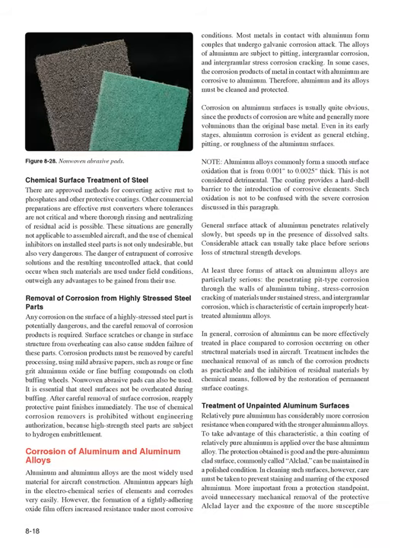Chemical surface treatment of steel. There are approved methods for converting active rust to phosphates and other protective coatings. Other commercial preparations are effective rust converters where tolerances are not critical and where thorough rinsing and neutralizing of residual acid is possible. These situations are generally not applicable to assembled aircraft, and the use of chemical inhibitors on installed steel parts is not only undesirable, but also very dangerous. The danger of entrapment of corrosive solutions and the resulting uncontrolled attack that could occur when such materials are used under field conditions outweigh any advantages to be gained from their use.